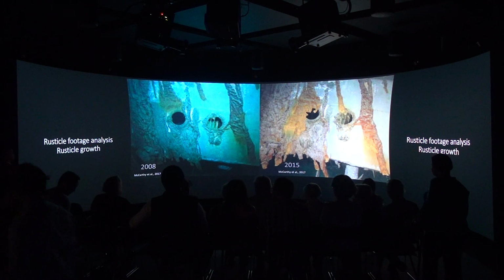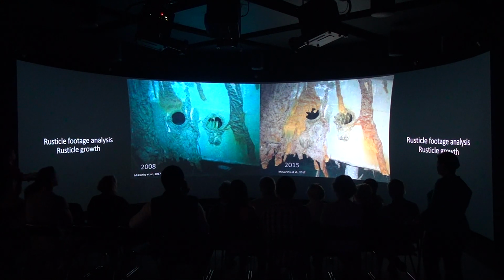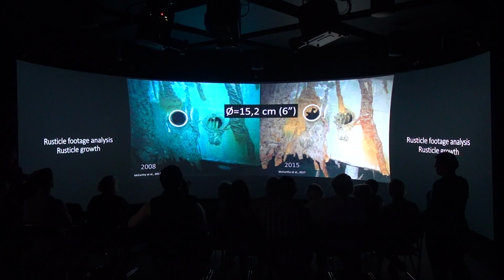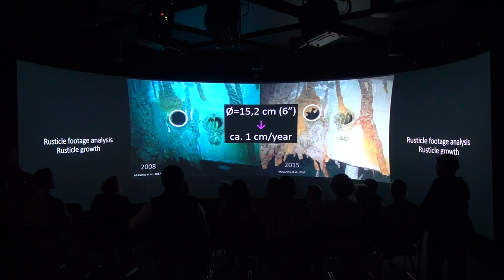So continuing with the analysis of the footage, these two images were published in the book. One is from the 2008 expedition, and the other one from 2015. So you can see the same part of the shipwreck, but 7 years apart. After a lot of research, I found the measurements of these little portholes. Well, not so little, 15 centimeters in diameter. So the rusticle in this image has grown to about half of it. So it's about 7 centimeters in 7 years, which gives us a growth rate for the rusticles of about 1 centimeter per year.